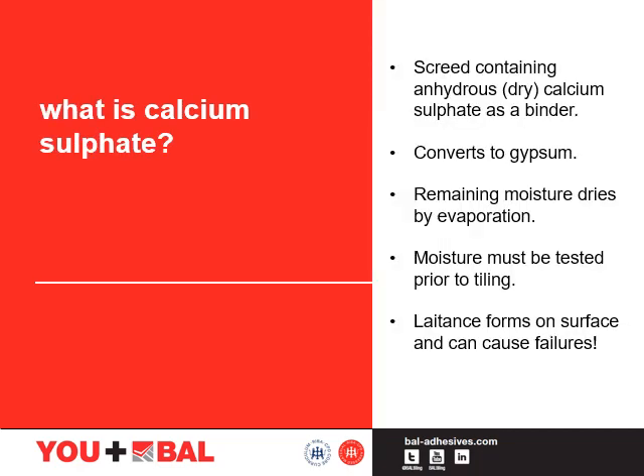A calcium sulphate screed is a screed containing anhydrous calcium sulphate as a binder. This converts to calcium sulphate dihydrate, gypsum, when water is added. The chemical process completes within 3 to 7 days. The remaining moisture dries by evaporation. Now this can take considerable time depending on the amount of water and the thickness of the screed. The moisture should be tested prior to tiling. The laitance should be removed correctly and in full, and the heated screed should be commissioned prior to tiling.